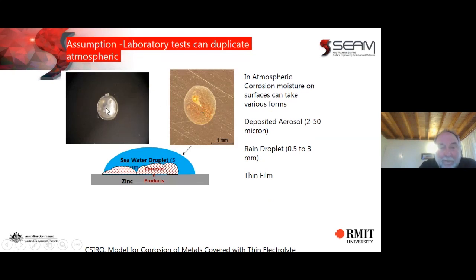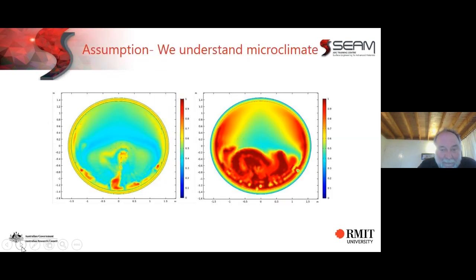And our experiments were derived from electrochemistry in solution, when in fact corrosion mainly occurs by fine droplets. The droplets are in two ranges: 2 to 50 microns is the deposited aerosol, or 0.5 to 3 millimeters if they are raindrops. Whereas experiments, as we mentioned, are in solution on a microliter amount. So there's quite a different scale between our electrochemical test and what actually happens on the surface.